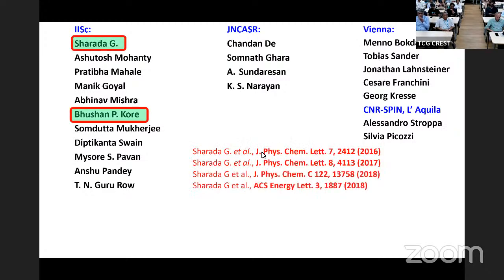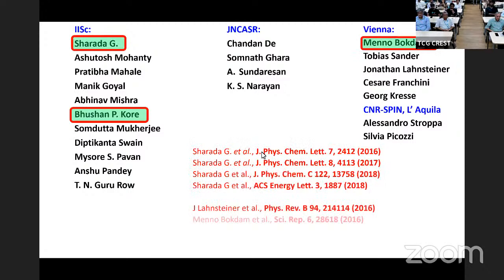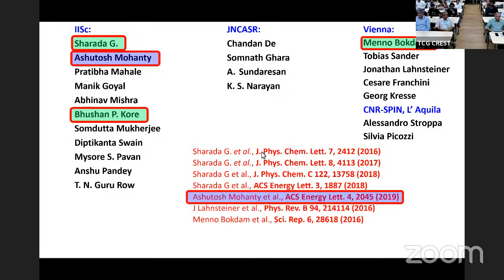Also, we collaborated with them. So it was initially driven mainly by Sharda and Bhushan. Then later on, Ashutosh also, who's now at Los Alamos, contributed very significantly. We showed, first of all, that it's not a ferroelectric material. The dipoles are disordered, they're dynamically disordered.